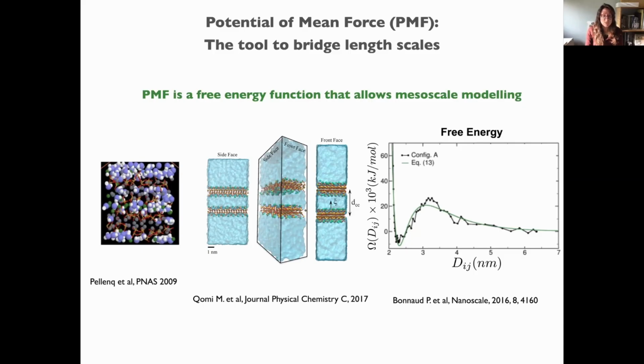Here it's an example for tobermorite in the middle, immersed in water. We move these layers of tobermorite to different distances and compute the free energy. From the free energy, we can then obtain the interaction between these particles.